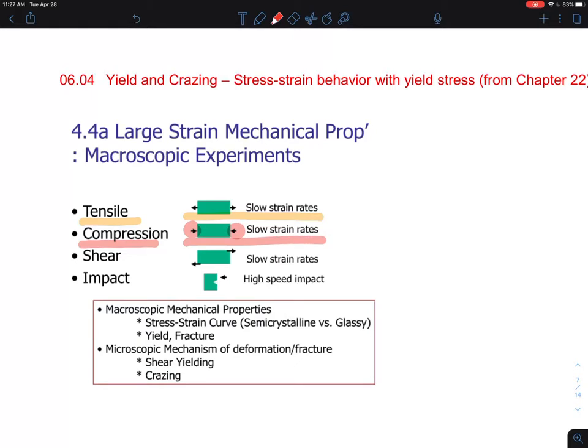You can think about that's the opposite side of the tensile mode. And then that mode is going to have some mechanical behavior that is actually different. And also there is something called the shear mode, which is kind of sliding the two planes. This is typically done in trying to measure more or less viscoelasticity of the material, whereas the tensile and the compression mode is more for the material in the solid state. And some of the deformation is actually at very high impact. The response is different from slow deformation. And this is called the impact strength or the impact mechanical properties.